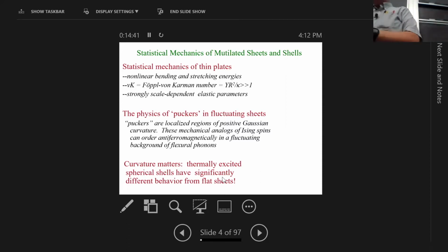The Young's modulus of this crumpled piece of paper is 10 to the 6th. And you know, if you can figure out the fractal dimension of this object when I crumple it, publish. It's not easy. It's a very non-trivial problem, even in classical physics. And you'll see that the result of this large Foeppl-von Karman number at finite temperature is strongly scale-dependent elastic constants. So elastic constants aren't constant. They actually depend on the size of the system in a highly non-trivial way. It's not just like a logarithmic dependence on system size. It's something that's very strong and seems to have been observed experimentally.